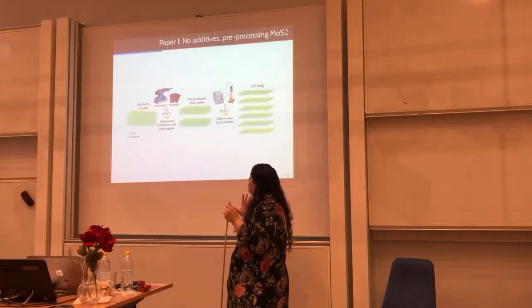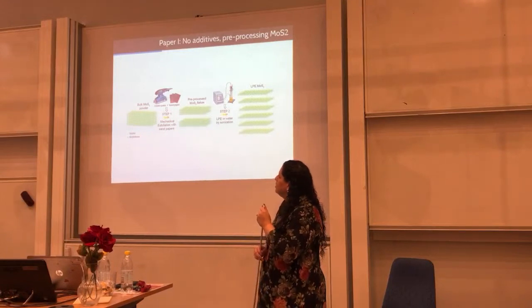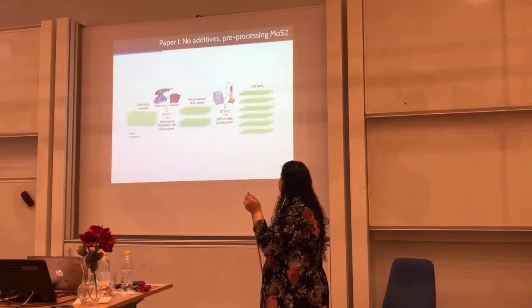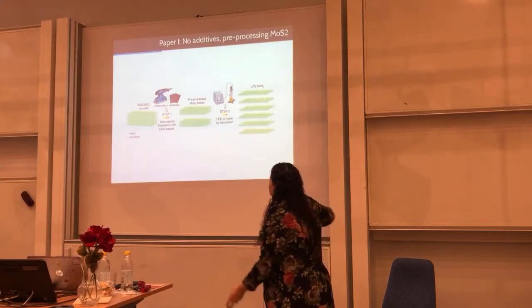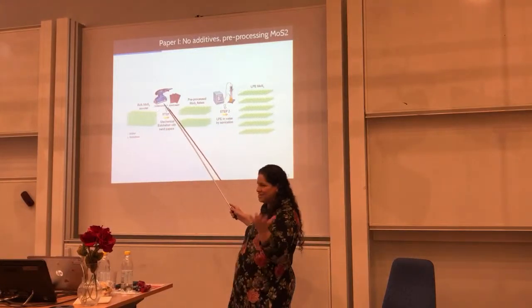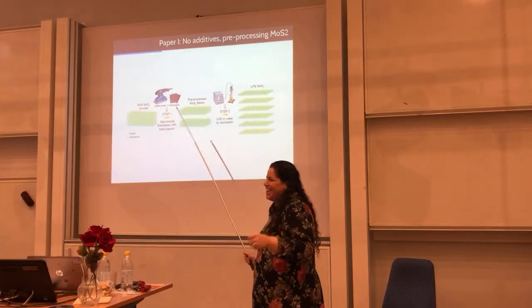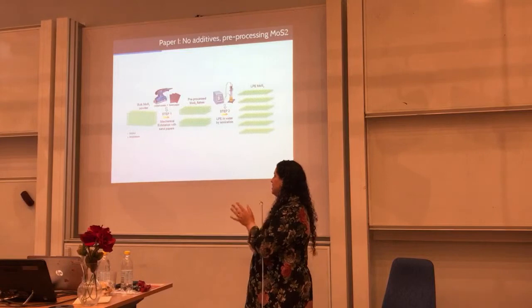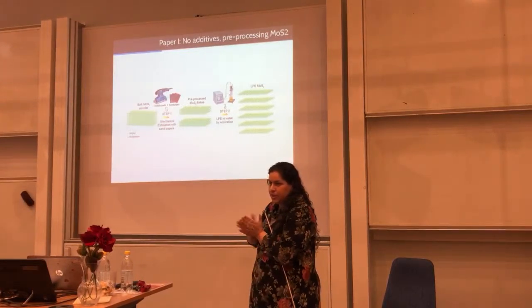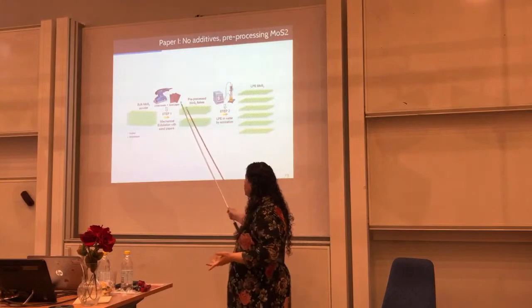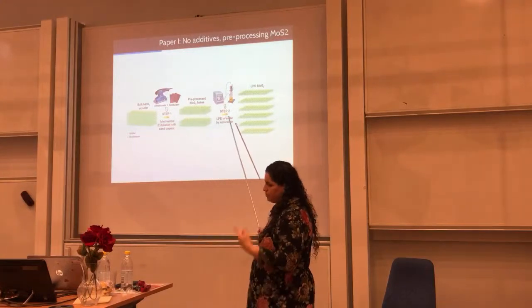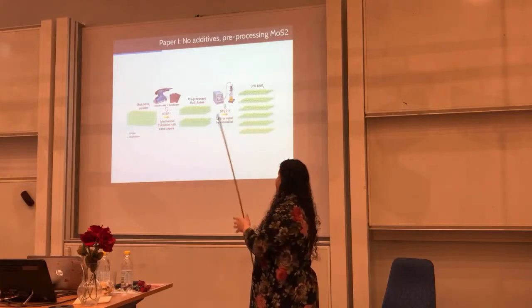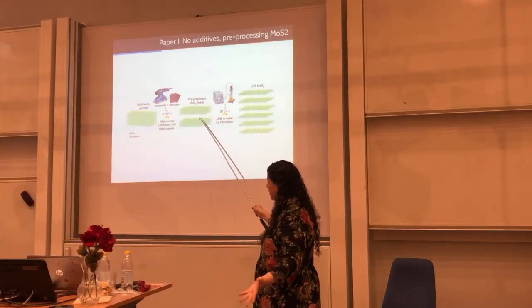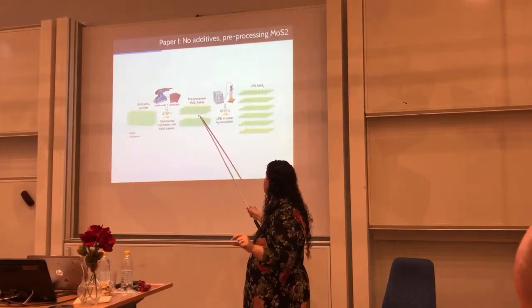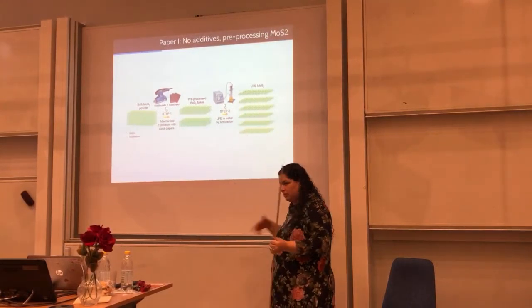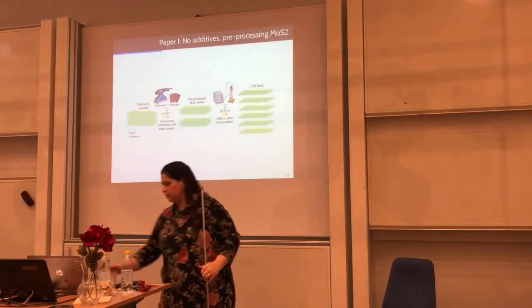So paper one, in a nutshell once again: we took the bulk molybdenum and used a very scientific tool to exfoliate it. This is our orbital sander, because it will exfoliate by friction. We sand papers, then we collect this exfoliated material and reprocess it in liquid. We expected that there would still be a stack of materials there, and then we individualize it by adding even more energy to it in water.